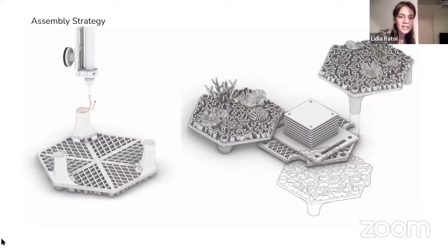As I mentioned, we had to print legs for the tiles as well. The way that we did that is that we would print the grid layers, then we would print the coral layers. We would wait for them to dry for about 4 days, and then we would flip them and print the legs. And then we created assemblies with 3 tiles holding the coral fragments and 1 tile holding the arms. And there's no formal deviation, there's no mass customization because we need to be able to trace the results.